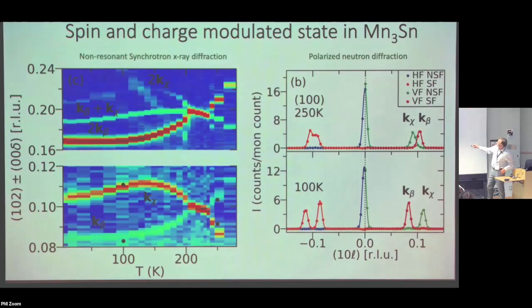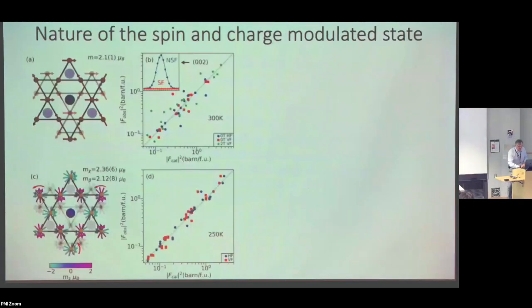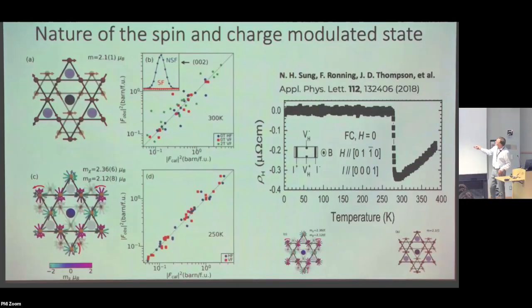And there you could actually see this. We had 2 components of wave vector that are converging on each other. Then for a brief period of temperatures, they stick together at the same value, and then they separate out and become separate traces. So it's a really quite complicated incommensurate structure that develops. And when that structure develops, we completely lose the Hall response. So this is in the commensurate phase, in the antichiral state. But once all of this rotation takes place, then we just totally lose it.